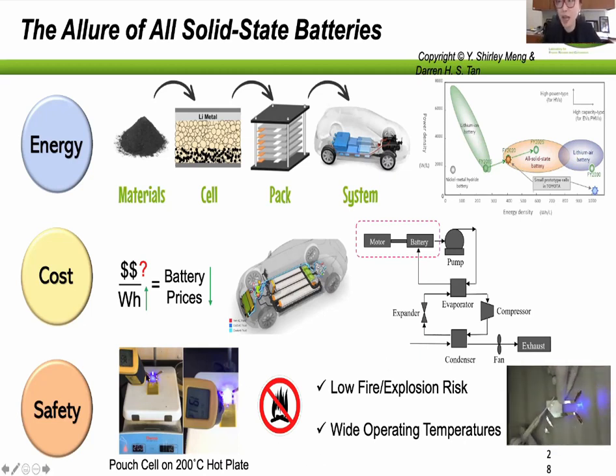And we can also put the battery on a 200 degrees Celsius hot plate, and it will work. So clearly the driving force for solid state battery is the high volumetric energy density, because you solidify everything. And you can actually abuse it, it has very low fire and explosion risk, and can operate in a wider temperature range. And the assumption that wider temperature means less thermal management is actually false. It's not correct, but that's always how we wanted to champion the field for solid state.